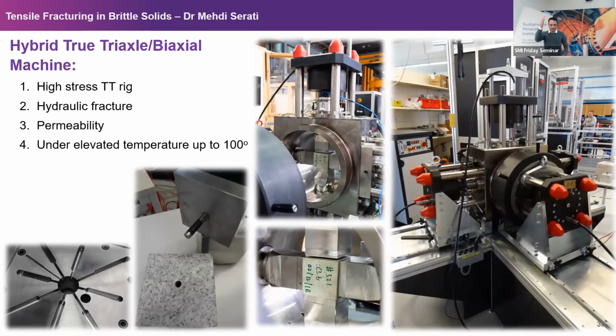Yes, the thermally induced spalling. I didn't show it to you, but we are working with our fire group and they have made quite an advancement in this area, and I'm fortunate to be working on two PhD projects together, one as the principal, one as the co-advisor. Inside the cell, you can go all the way to 200 mil. So imagine a 200 mil cube, which is quite decent, really. Then you drill a hole, and this hole could be across the thickness, or you may close the end, so it generates more of a tunneling environment.